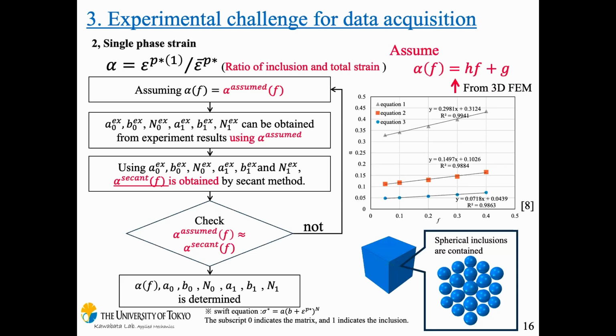Now I explain how to decide alpha. First we assume alpha, and using the assumed alpha, we can get the single phase constitutive equation from the experiment data. But we don't know whether the assumed alpha is correct or not. So next, using the obtained single phase constitutive equation, we solve the second equations again, and we calculate alpha again. This alpha we call secant alpha, and finally we check whether the assumed alpha and secant alpha are the same enough or not. If they match, we can get the single phase constitutive equation. This kind of convergence calculation we conduct.